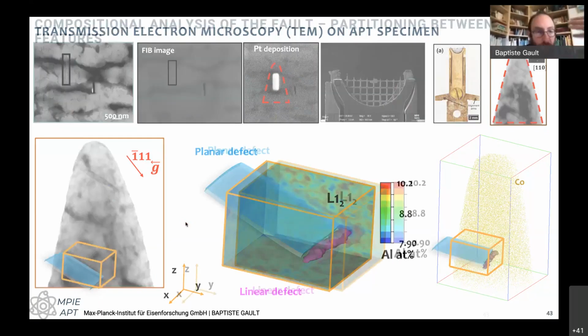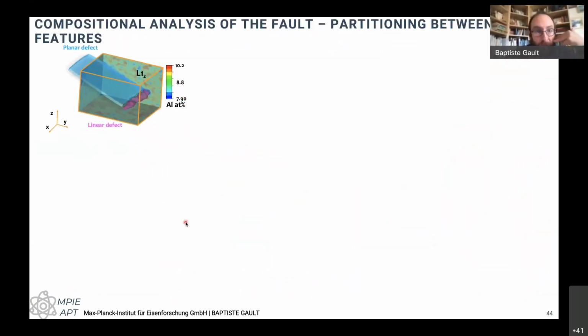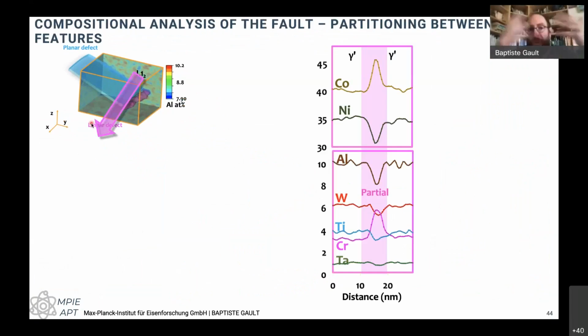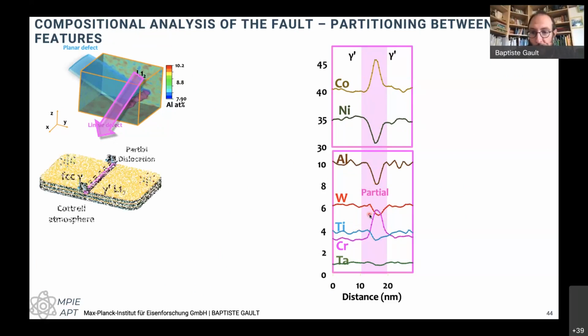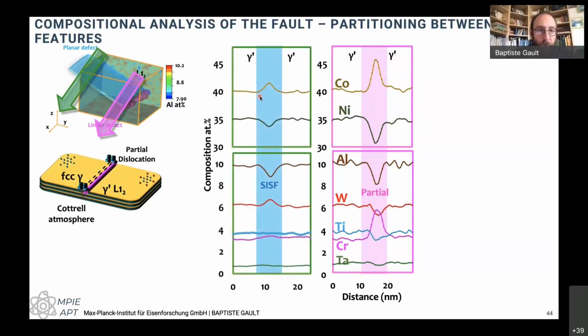The interest of the atom probe comes now, and its strength is that we can interrogate this point cloud in whichever way we want locally. So we actually looked through the linear defects, this partial dislocation. We can see effectively a very strong segregation of chromium, depletion of nickel, segregation of cobalt, depletion in aluminium, and in tungsten a little bit. We can then also look through the fault itself. We see a slight segregation of cobalt and tungsten, depletion of aluminium and nickel.